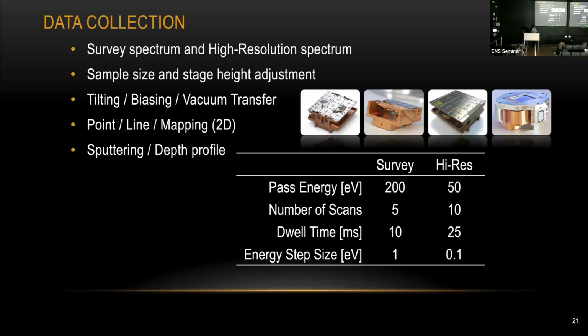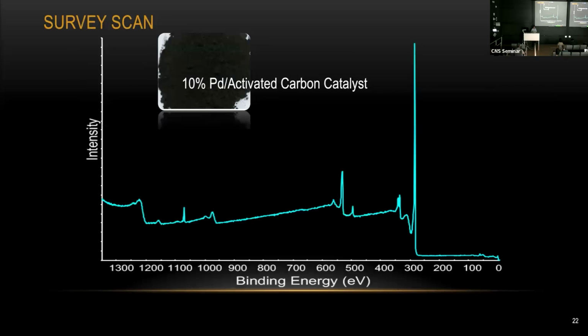And when you do the measurement, there are really just two types of data you're going to get. For XPS measurement, you're going to get a survey spectrum and also a high resolution spectrum. High resolution spectrum just means a narrow scan for a certain element. So those are the only two types of data you're going to get most of the time. Here is a survey spectrum for one of my very early samples, which is 10% palladium in some kind of carbon catalyst. We do a quick survey, and that's the data you can see most of the time.